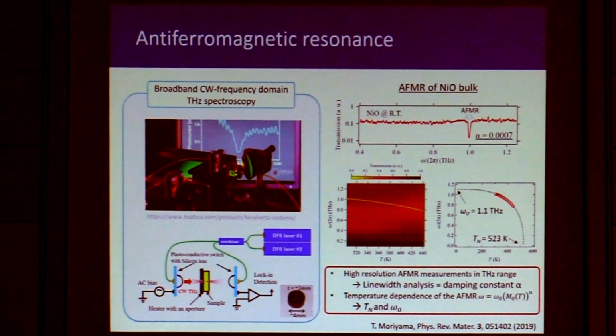So it's a kind of proximity effect? Meaning you get an induced moment in the platinum? No, you can have surface magnetization. If you cut your sample, you always have a non-compensated magnetization at the surface. You have this spherical particle. It's not an ideal interface or something. Experimentally, we cannot really see that.